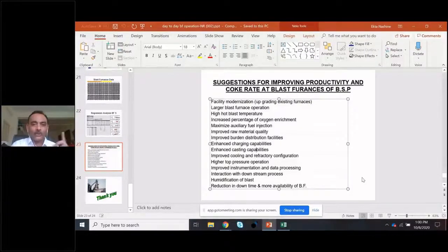What happened? All the tubes surrounding the furnace fill with liquid iron and slag. The furnace will stop. The furnace will choke. So casting capability means continuous removal of hot metal and slag. It must be faster than the production rate.